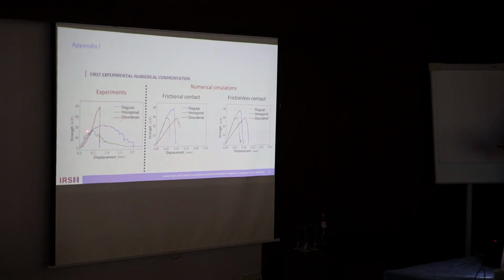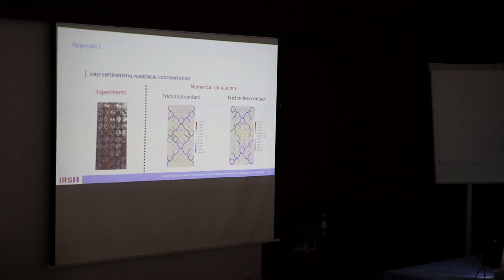Here is the comparison between the ultimate strength I obtained for the different types of sample, and here is the experimental one. So we can see that we obtain good order of magnitude, but maybe the point in which we have to work is the probabilistic part of the failure mechanism. So here, as the stress field is approximately the same in all the sample, we obtain decohesion everywhere during numerical simulation. In contrast, we can see here that the decohesion is located in a single fracture.